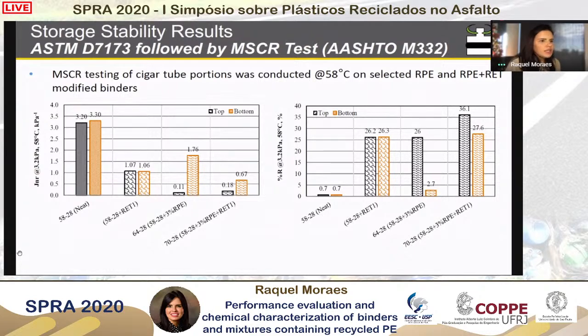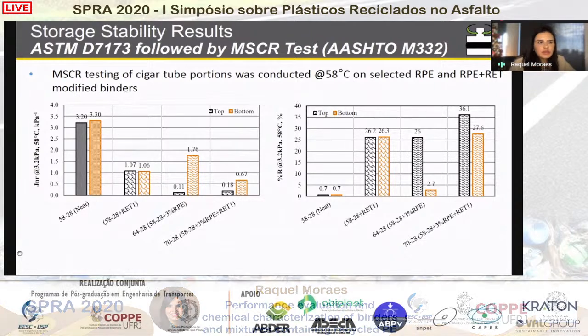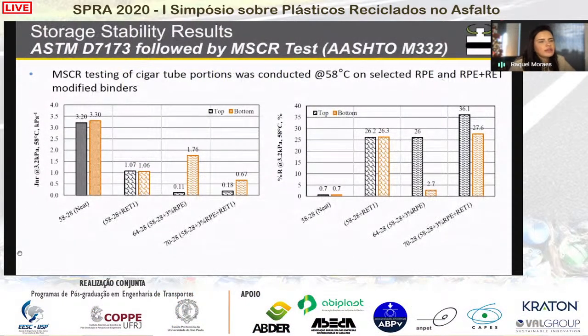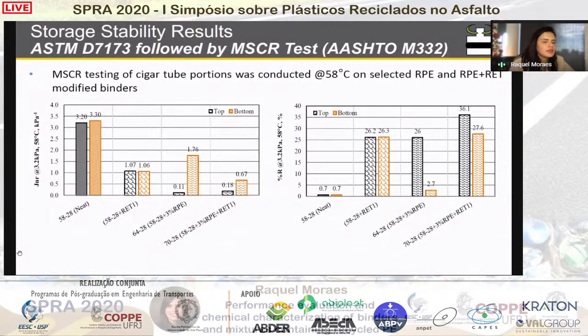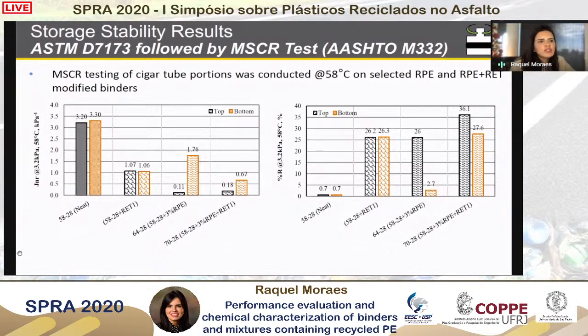And here, as illustrated in the graphs on the left and the right side, the gray columns are the top and the orange columns indicate the bottom samples. We can see that both the neat binder and the terpolymer modified binders had very similar JNR and percentage recovery values for the top and bottom samples. However, the binders that were modified with the recycled plastics, and with the recycled plastics plus their terpolymer, showed lower JNR and higher strain recovery between the top and bottom samples, which is an indication of polymer separation. And also from these results, we can see that by adding the terpolymer to the binder modified with recycled plastics, we can decrease the severity of phase separation, but we cannot mitigate the problem completely.